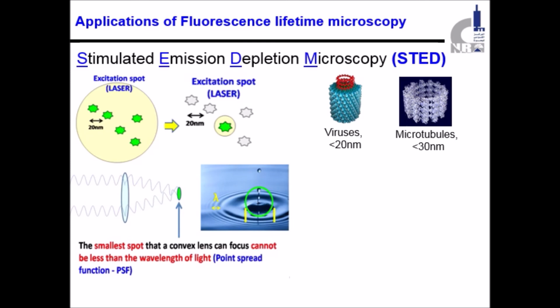However, it is impossible to achieve a very small excitation spot reaching 20 nanometers or below. This phenomenon is known as the point spread function, which states that the smallest spot a convex lens can focus cannot be less than the wavelength of light. As we have a laser source of 500 nanometers, the minimum spot size cannot be below 500 nanometers.